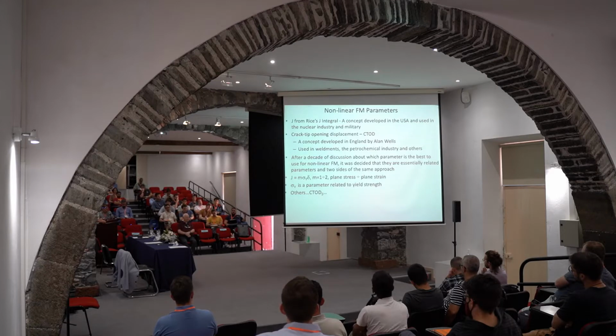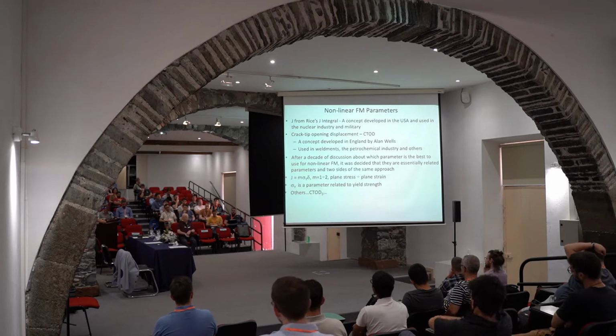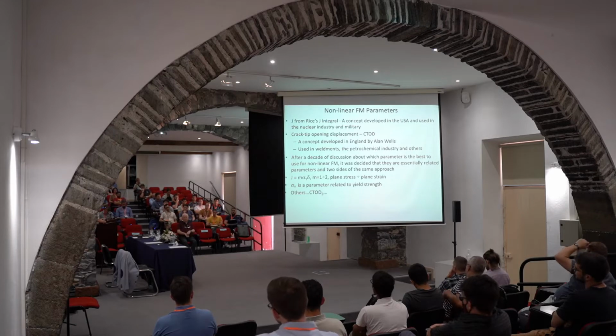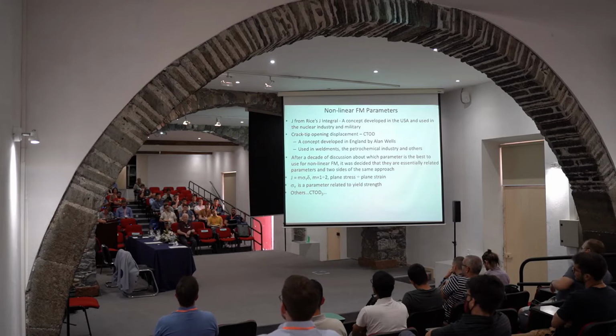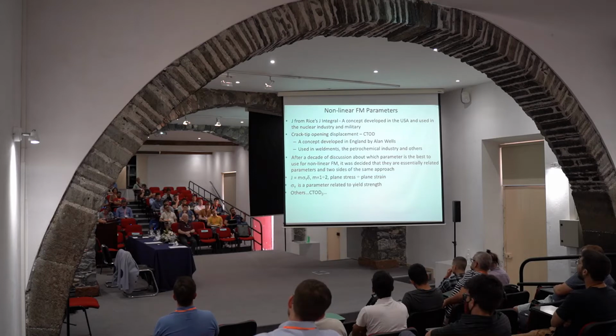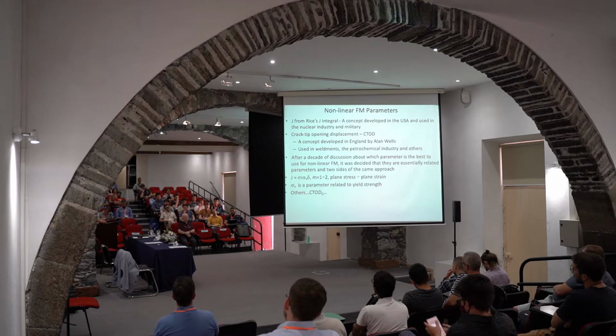Well, this is so because crack tip opening displacement is mostly an empirical parameter, whereas J is very soundly based in continuum mechanics. Anyhow, crack tip opening displacement is a valid parameter, it works, and as people say, we use it and do not excuse it, regardless of the fact that we don't have a theory background.